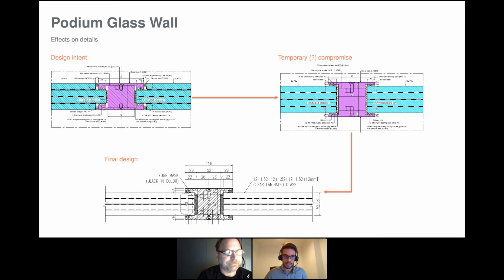So what you can see on the bottom is the final design from GNM, which is basically based on ours, where we have the glass clamped from outside of its thickness by this clamping plate. So no recess in the glass. Luckily, all the other details were maintained, especially the visible ones, and GNM with the drawings was very consistent with our design. So they did a very good effort in trying to maintain as much as possible all the details that we had in our intent.